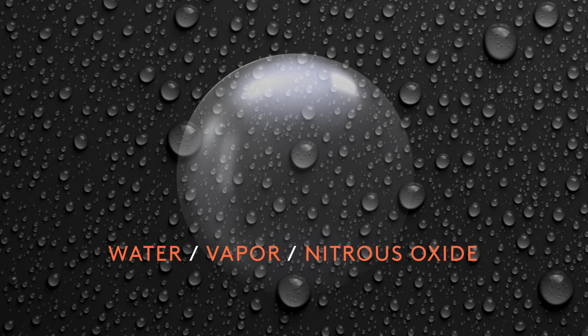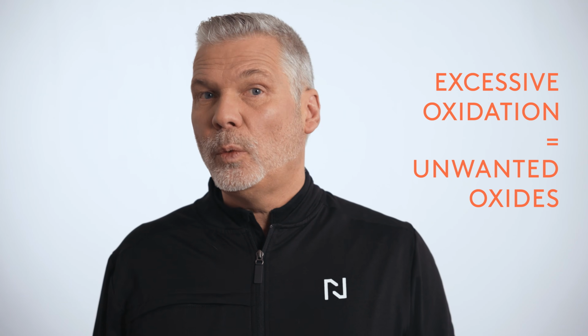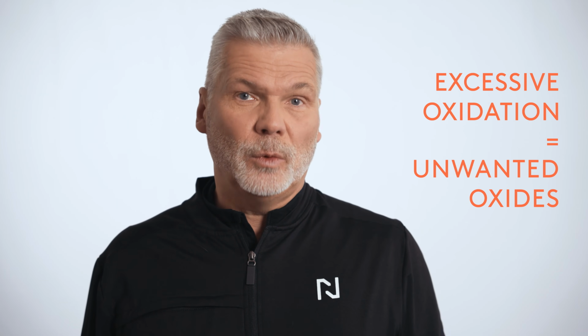There are several different ways of oxidizing surfaces, and each one requires a controlled time and temperature. The process can also be controlled using an oxygen probe because excessive oxidation will lead to the formation of unwanted oxides. At the end of the process, you should achieve the desired thickness of magnetite.